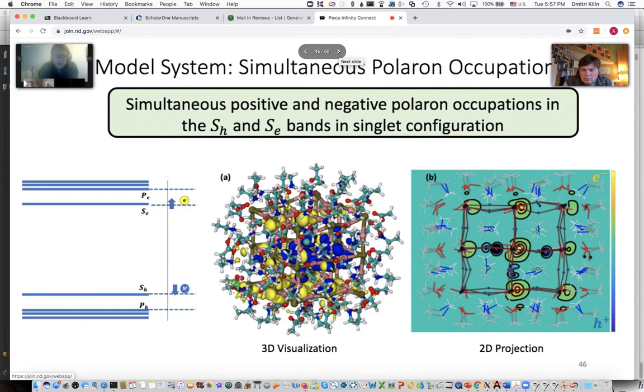And then our model is to essentially combine both these models, so to reflect the photo excitation of a physical system. So if you photo excite and then let the charges cool, you would have an electron occupying this SE band and a hole in this SH. And those are visualized in this middle and right figure. And it shows that you would have a different potential acting on the nuclei because the charge isn't uniformly distributed. So you have positive charge located in some regions and negative in others. And so that will influence the dynamics of the couplings.